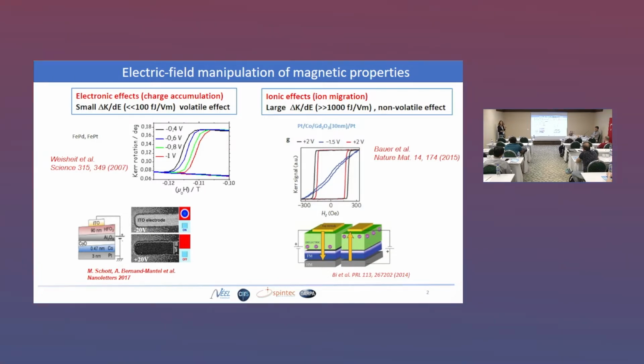A bit more recently, we found, this time using a solid gating, that in platinum cobalt alumina we could change the different magnetic energies in order to switch with an electric field the platinum cobalt alumina from a system in a state in which you have skyrmions to one in which the skyrmions were annihilated, and we call this the skyrmion switch device.